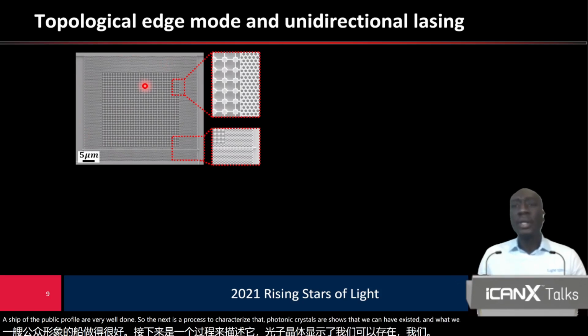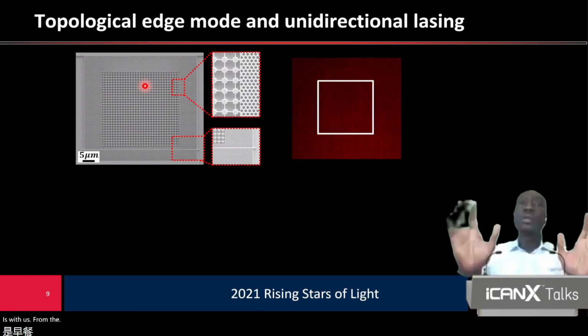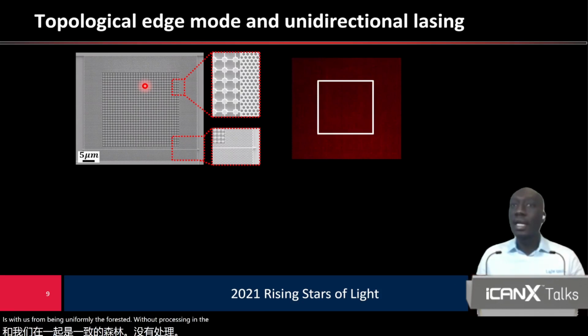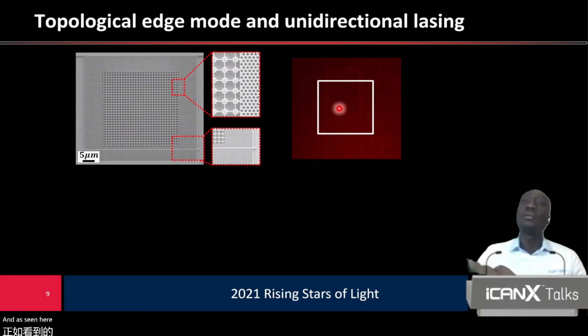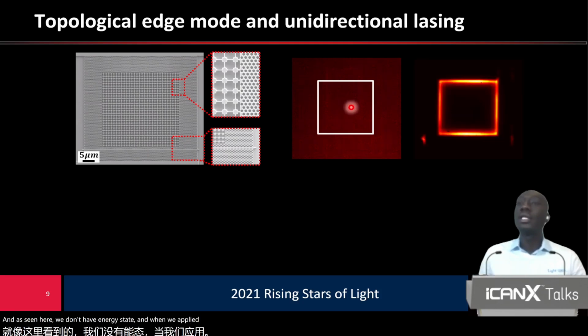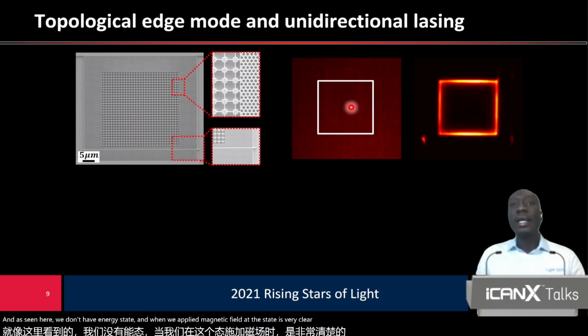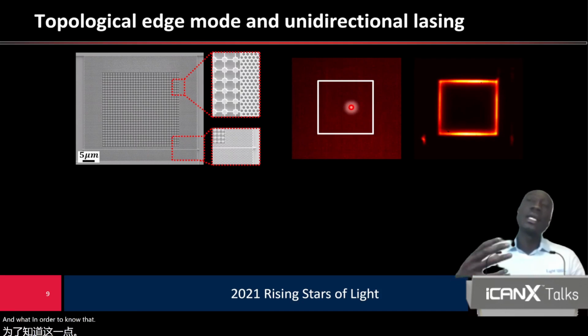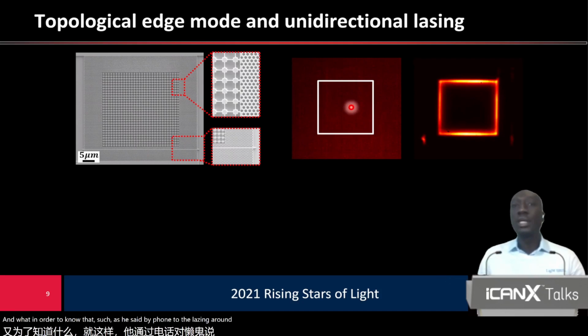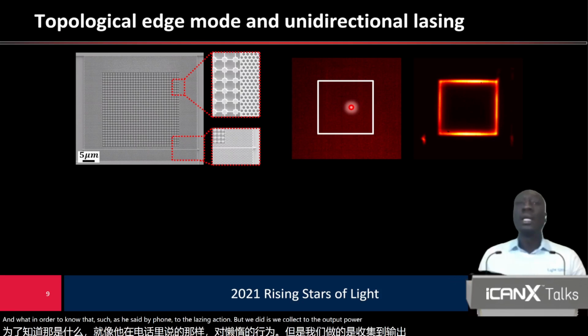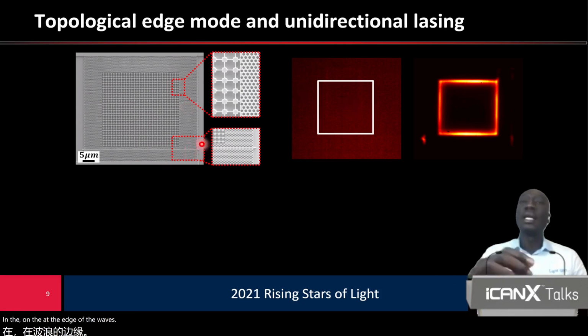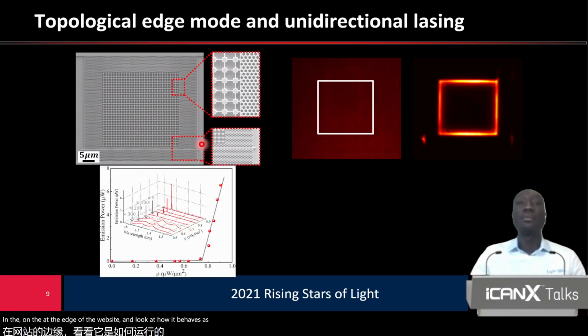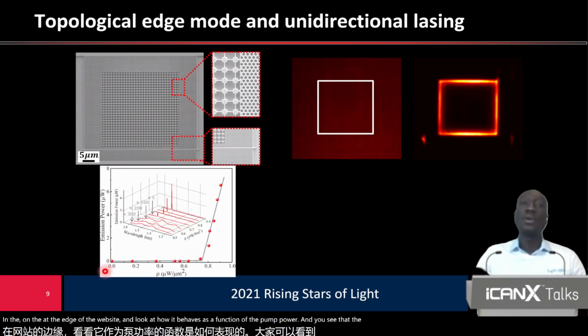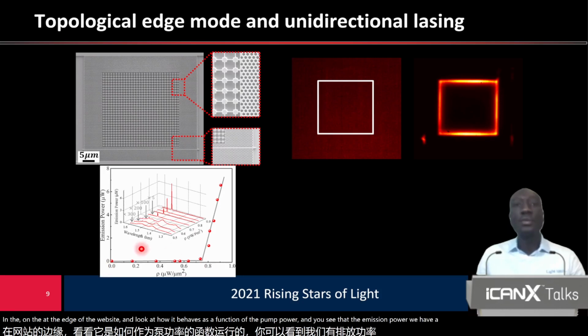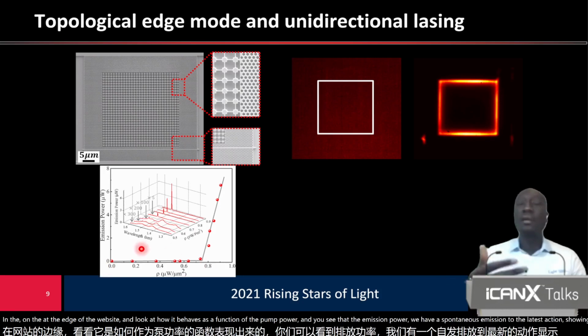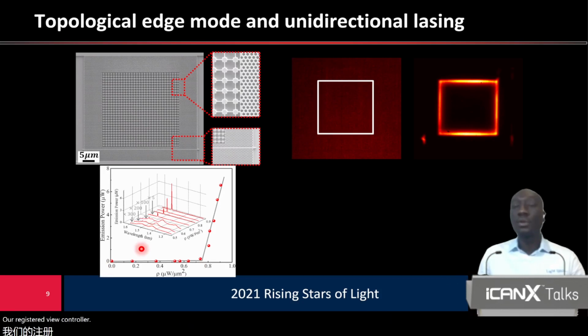So the next step consists of characterizing such a photonic crystal to show that we can have an edge state. What we did is we first pumped uniformly the whole structure without applying any external magnetic field. As seen here, we don't have an edge state. And when we apply a magnetic field, the edge state is very clear. In order to know that such an edge state corresponds to the lasing action, we collected the output power at the edge of the waveguide and looked at how it behaves as a function of the pump power. You see the emission power goes from spontaneous emission to the lasing action, showing that our edge state corresponds to lasing.